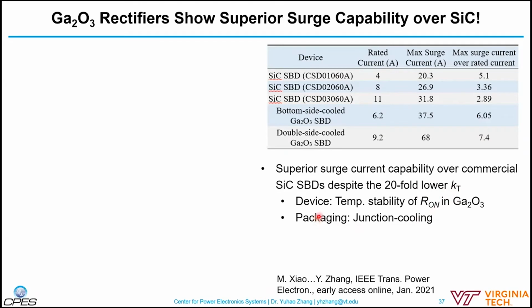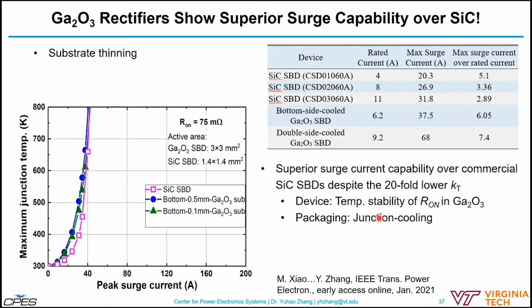And that is attributed to two key factors. On the device side, the temperature coefficient of the on resistance is much smaller in gallium oxide compared to silicon carbide. So the on resistance increases much more slowly with temperature in gallium oxide. And on the packaging side, by using this junction cooling, we essentially don't need to extract the heat through the gallium oxide substrate. So finally, let's look at several different ways to further improve the ruggedness of gallium oxide devices.